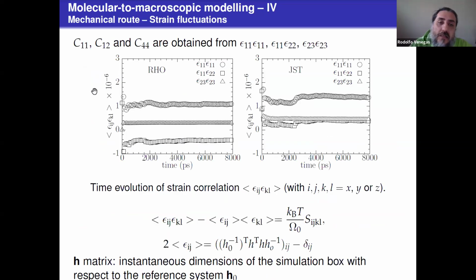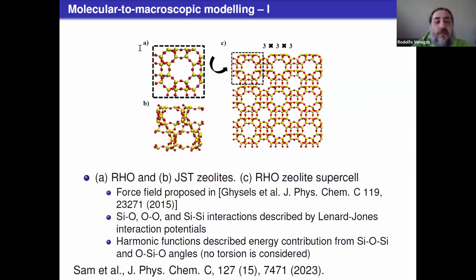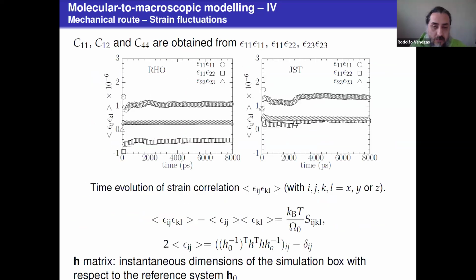And the second route is to get C11, C12, and C44. These are the elastic parameters, and only these three because we have materials with cubic symmetry here. So three elastic constants are sufficient to describe the whole elasticity tensor. And then we have the evolution of the strains, the cross strains, with time. When we reach a certain convergence value, we can work out the value of the strain products, and with this formula we can work out the compliance tensor, S, and from the compliance tensor we get the elasticity tensor.